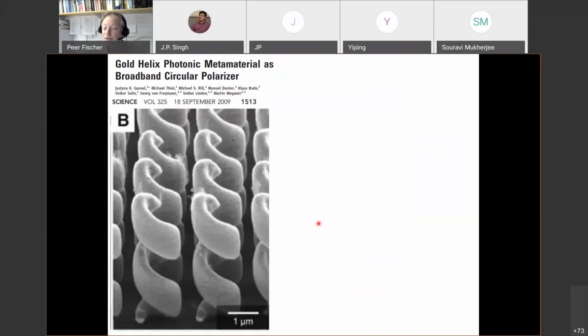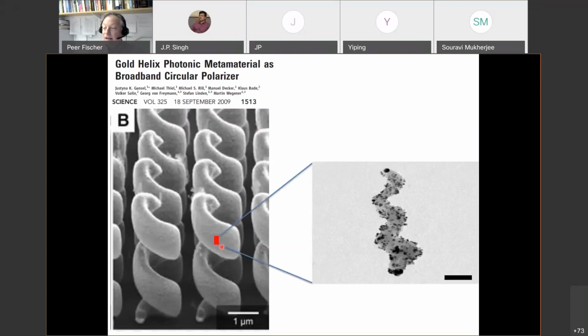And just to bring home how small these structures are that GLAD can make, here is a gold helix that was made with a polymer first, and then the polymer was turned into gold. It's a well-known paper in metamaterials for the infrared, and it was made using 2-photon lithography. Now, in 2-photon lithography, you have a voxel or a write pixel for writing, which is about 100 to 120 nanometers in size. But GLAD is, of course, able to do this much more easily. So in 1 pixel that you can write with 2-photon lithography, with GLAD you can make much, much smaller structures here, like this multi-turn helix.